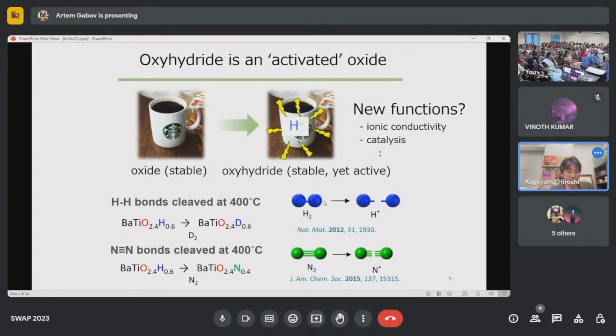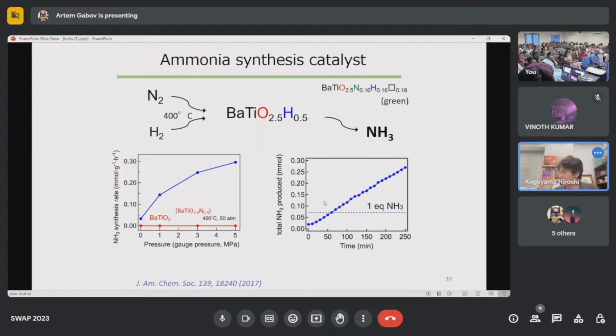Okay, so now we actually already observed that this material, the oxyhydride, has the ability to cleave the H-H bond in H2 molecules, and also independently we observed that the nitrogen molecule with triple bond can be cleaved at as low as 400 degrees C. Okay, this is just chemical reactions, but when we flow H2 gas and N2 gas at the same time, we observe that ammonia is generated, as you can see from this panel. In the case of the precursor oxide material, this doesn't generate any ammonia gas. But when we use the oxyhydride material, flowing H2 and N2 gives you ammonia with very high efficiencies.